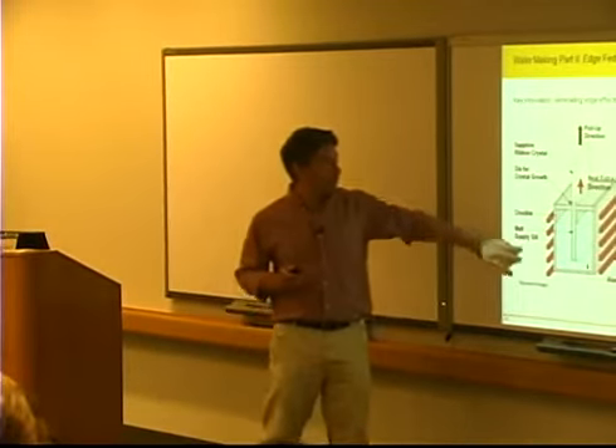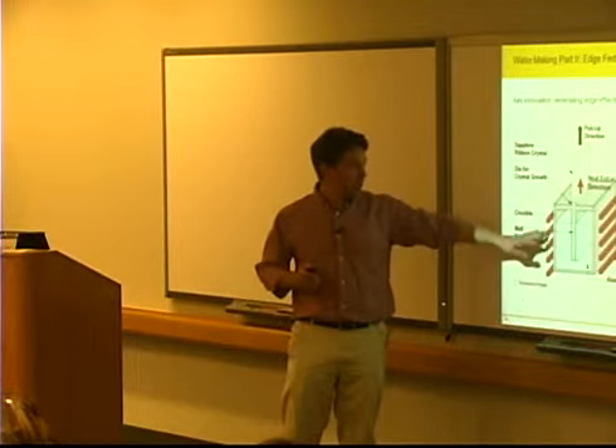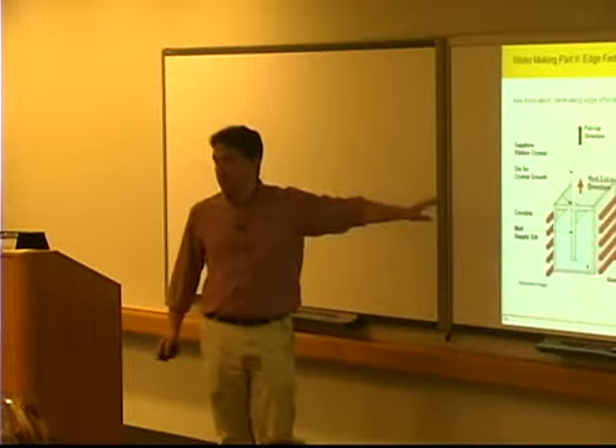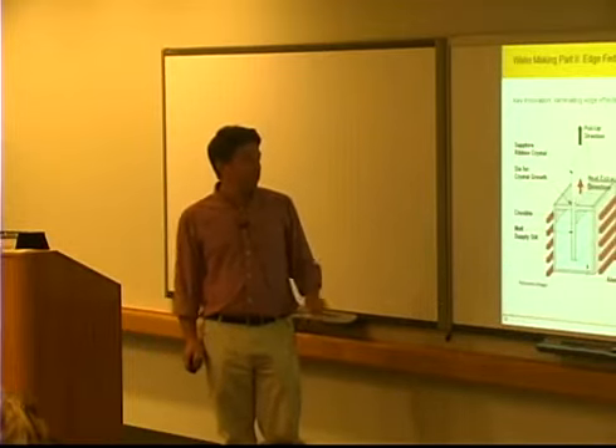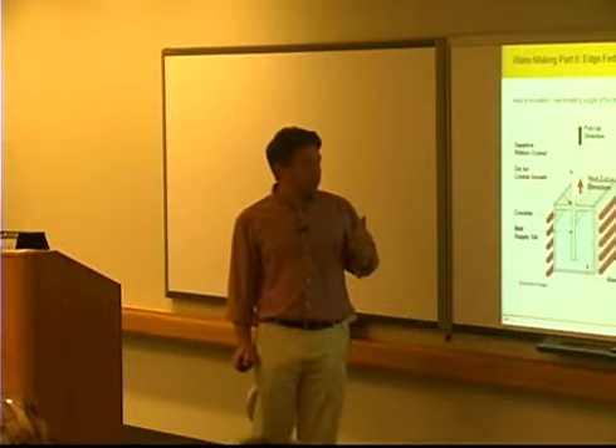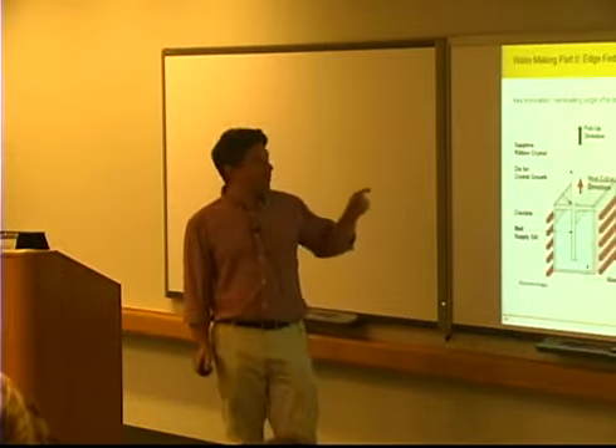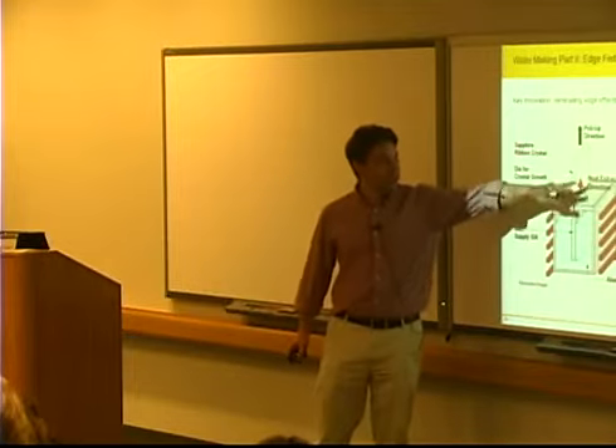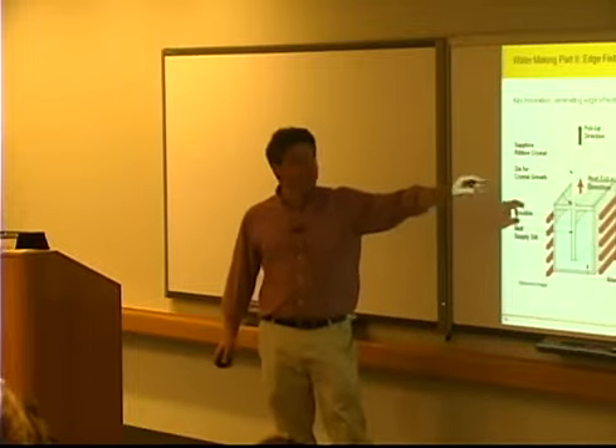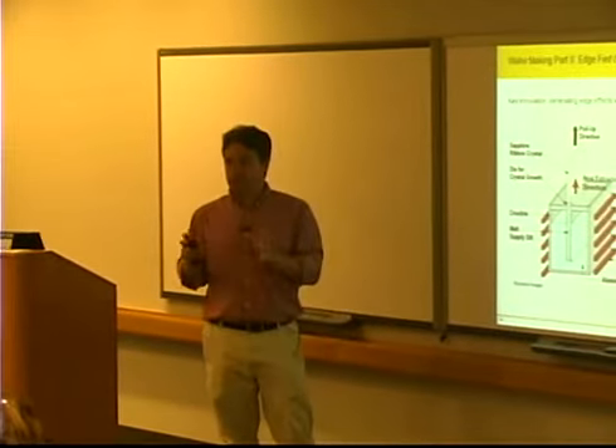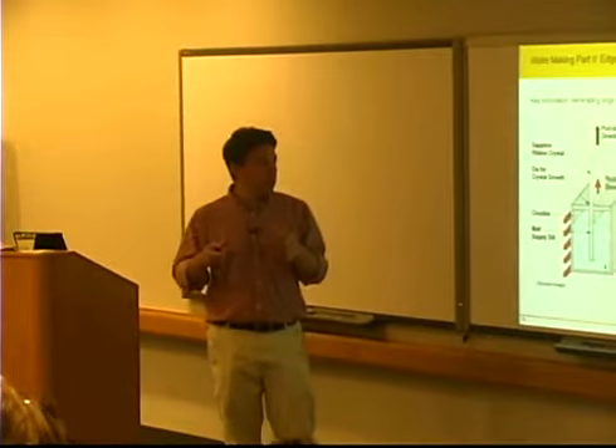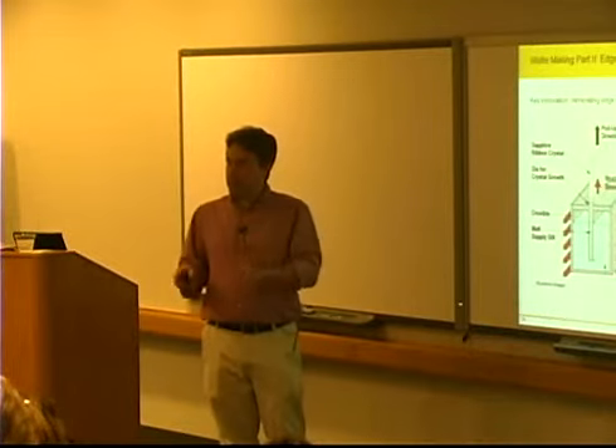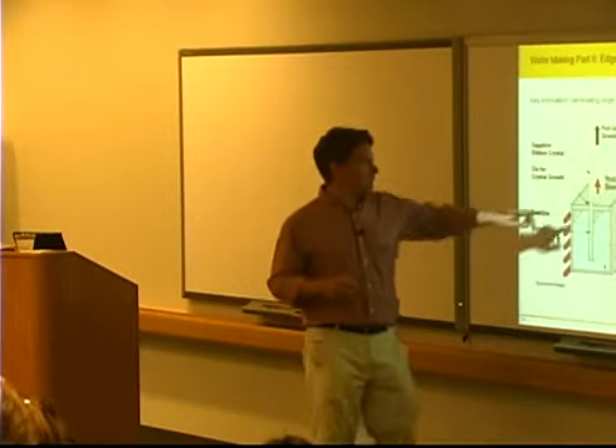And in this case, this figure is actually a figure from Kyocera, and this is for alumina, you'll notice. And alumina is actually made by this technique. But it was commercialized for silicon, and the main thing that they did that was really quite smart is they were able to eliminate their edge effects. There's a lot of instability around these edges of the wafers here. And they were able to eliminate that by making tubes. And they made octagonal and 9-sided and even 10-sided tubes where each side of the tube would then be cut into a wafer width. But the edge effects that you'd get here would be non-existent because it would be cut out in this little angle.